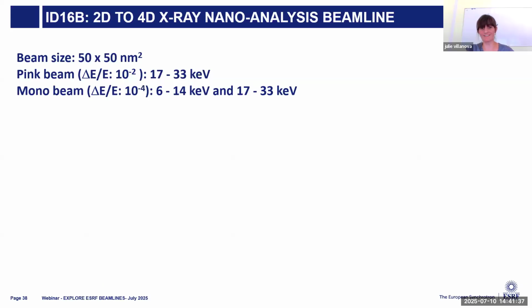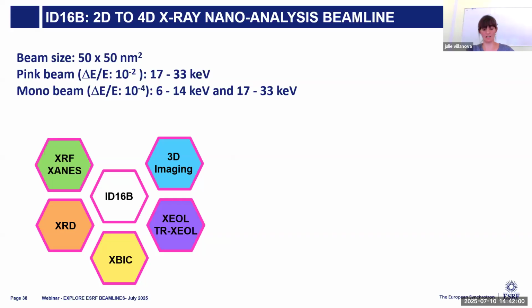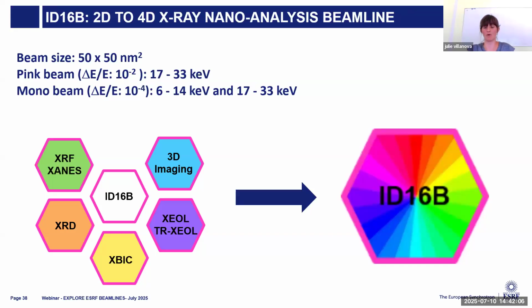So I will conclude this webinar. It was a lot of information, I guess, and maybe too much time. But the most important is that at ID16, we are a nanoprobe. We have a beam size of 50 by 50 nanometers. We can work in mono or in pink beam from 6 to 33 keV. We have different scanning techniques as well as 3D imaging techniques that we can use either simultaneously or one after the other. And since we have high flux and also space around the sample, we can offer and also adapt in situ and time-resolved experiments.